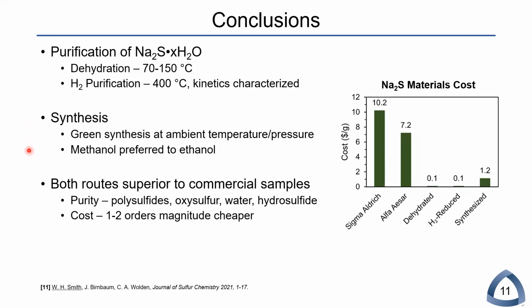And finally, we compared samples produced through either route to currently available commercial samples of sodium sulfide and showed that they are comparable to, if not superior to, both of them, not only in terms of purity, but also in terms of cost, as shown here on the right. We expect that the materials cost of either the hydrogen reduction or the synthesis process is 1 to 2 orders of magnitude cheaper than the currently available forms.